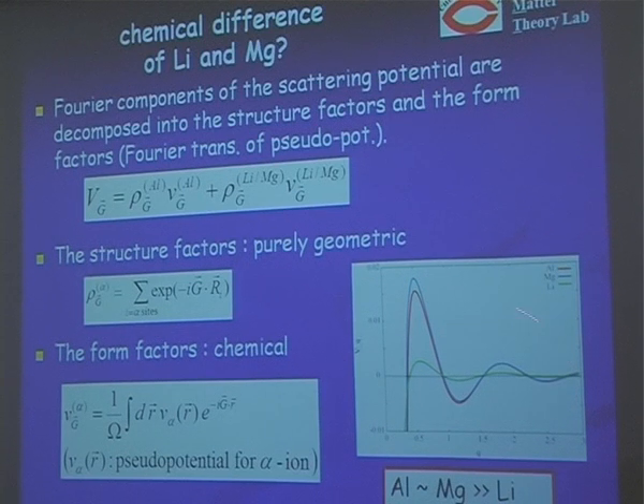So here is the form factor for aluminum, magnesium, and lithium. And you see the blue one is magnesium and the red one is aluminum. So they are very similar to each other. But lithium is very weak in comparison with aluminum and magnesium. So that means lithium scatters electrons very weakly.